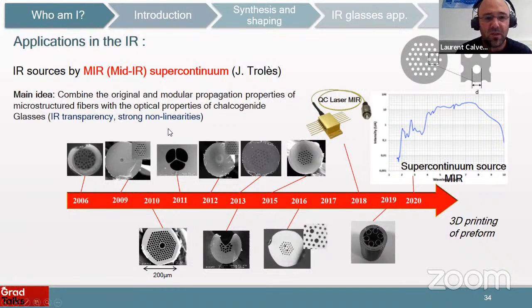It's just by using the infrared transparency of the fibers, of course, but also because when you use some heavy elements like chalcogenide ones, you will have some specific optical properties. And in this case, by using selenium, you will have strong nonlinearities inside the bulk, and you will be able to develop different modes of propagation of light. And it is with this kind of propagation, with this kind of modes, that you will be able to develop new infrared sources. And so this is very interesting for fibroscopy and different medical applications.